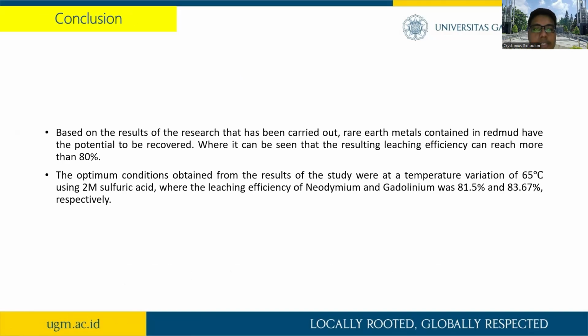Based on the results of the research that has been carried out, rare earth metals contained in red mud have the potential to be recovered, where it can be seen that the resulting leaching efficiency can reach more than 80%. The optimum condition obtained from the results of the study was at the temperature variation of 65 Celsius degree using 2 molar sulfuric acid, where the leaching efficiency of neodymium and gadolinium was 81.5% and 83.67% respectively. Maybe that's all from my presentation.